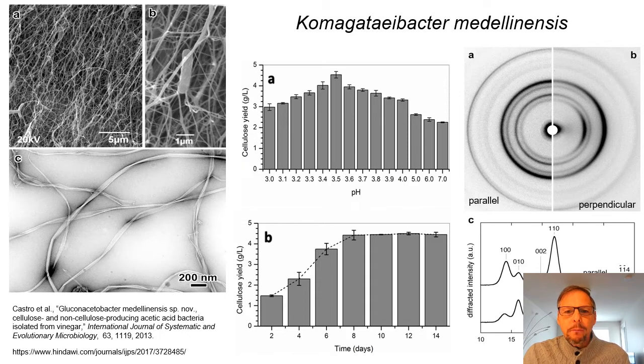There is an optimum pH that you can see there, usually in the acidic side of pH. And the yield with time, as the microorganisms produce cellulose, will produce more and more until some given time, in this case roughly a week, where the yield more or less reaches a plateau. So the more time you leave the microorganism to produce cellulose, then the thicker the pellicle will be.